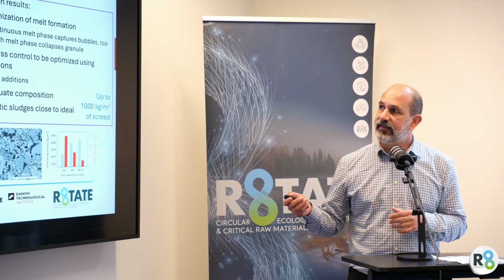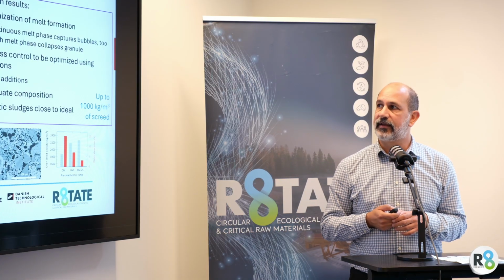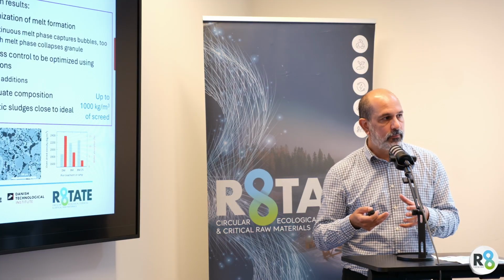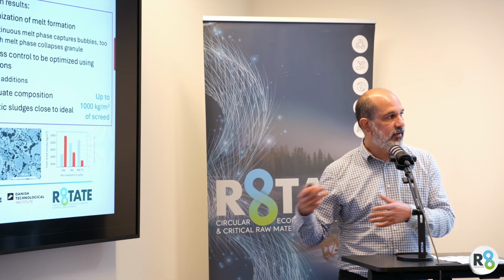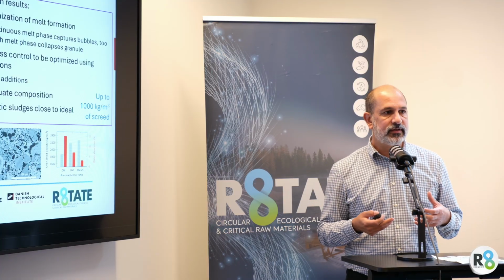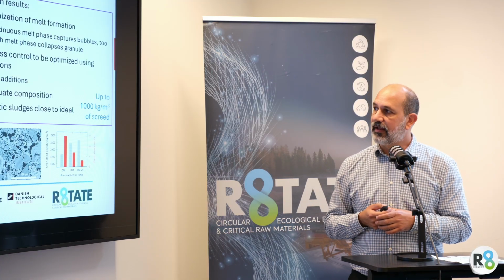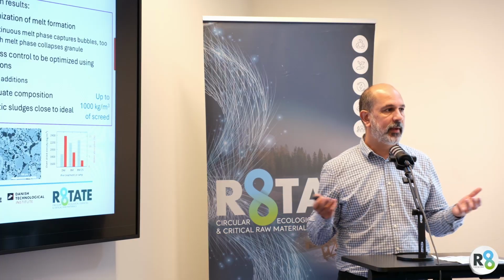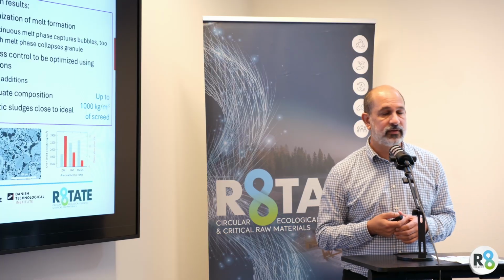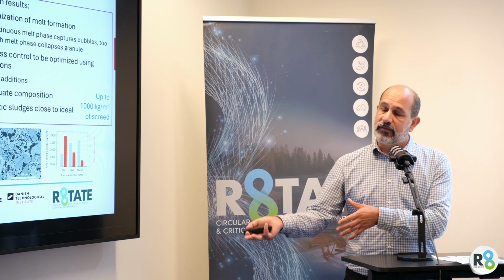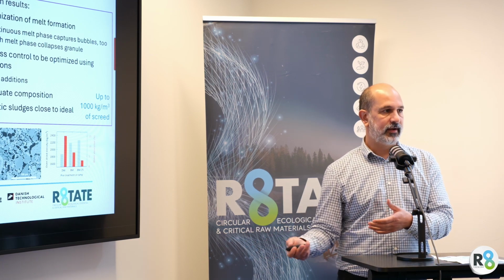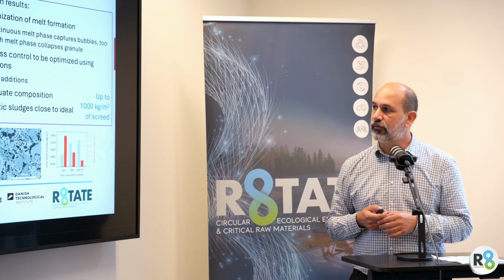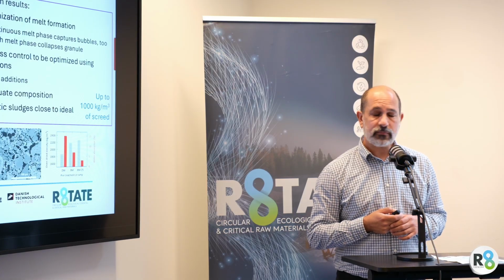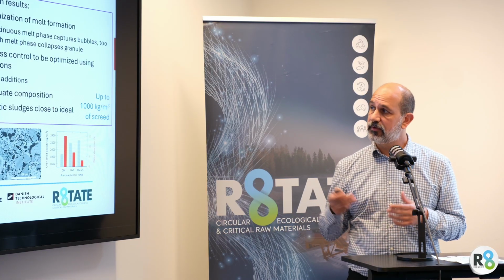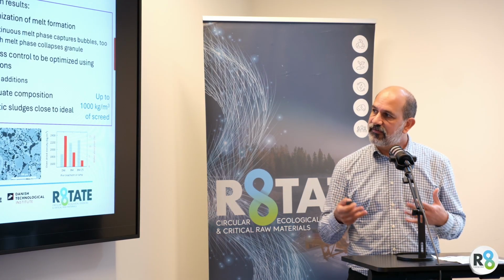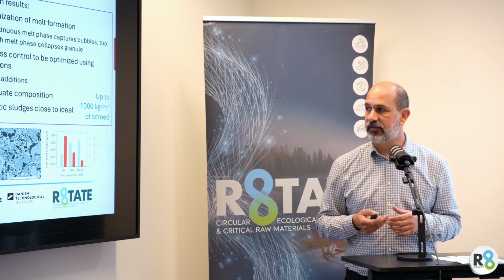And again, this is produced via calcination. First, some granulation of the particles, and then the calcination for sintering the material and producing these lightweight aggregates, which are normally expanded clay. That's the most common product in the market. But instead of using natural clays that are a primary resource, we were using this sludge residue as a secondary material, so increasing much more the circularity of this production.